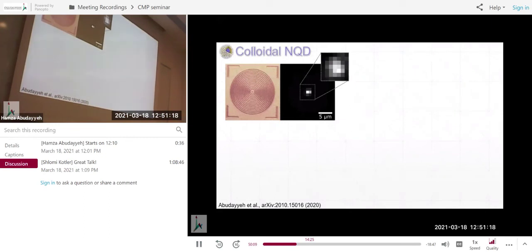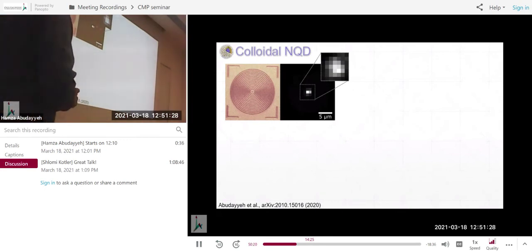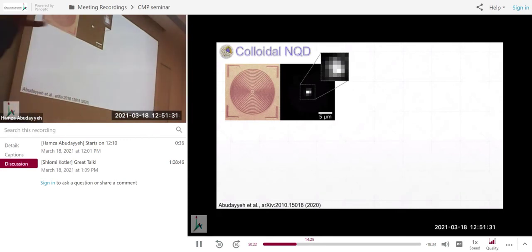So on the left, we're looking again at the antenna from the top. This is just a microscope image. And you see this little dot here. I don't know if you can see it clearly. This is the nanocone. On the right, I did something different this time. So instead of just exciting and looking at spatially, I did a confocal map. So scanning every point here, line by line, scanning the laser across to see if there are any quantum dots on the sides of this antenna. And you can see that it only emits when you're exactly at the center where the nanocone is.